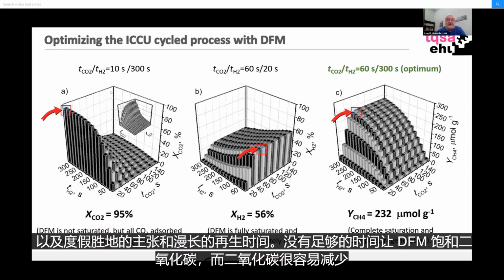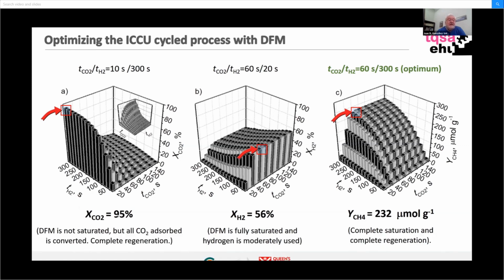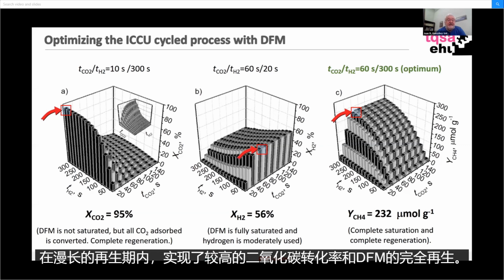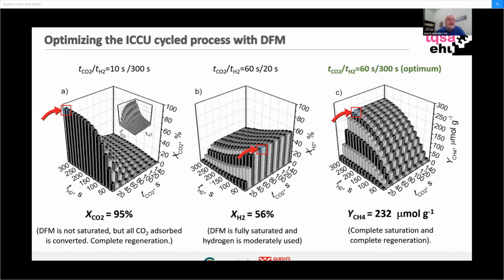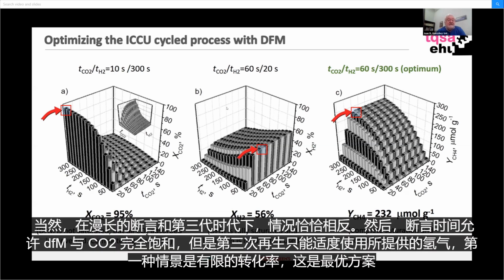Under a short absorption and long regeneration time, there is not enough time for the DFM to be saturated with CO2, which will be easily reduced during the long regeneration period, achieving high CO2 conversion and full regeneration of the DFM. The opposite occurs under a long absorption and short regeneration time. Then the absorption time allows full saturation of the DFM with CO2, but the short time for regeneration only provides a moderate use of the supplied hydrogen with limited conversion.